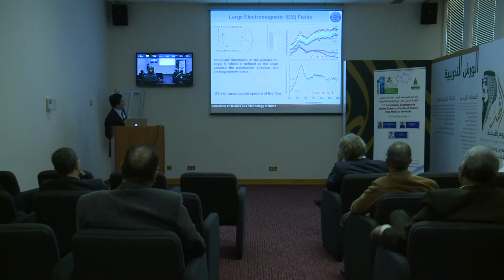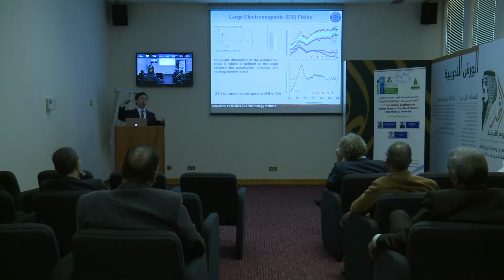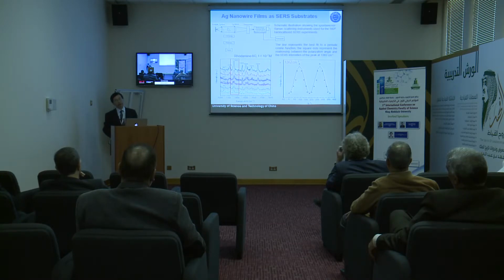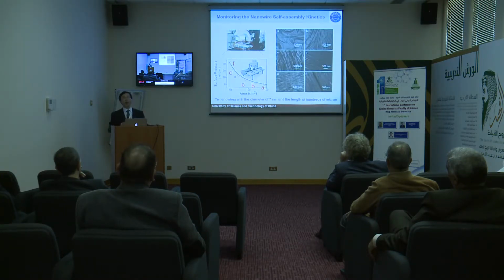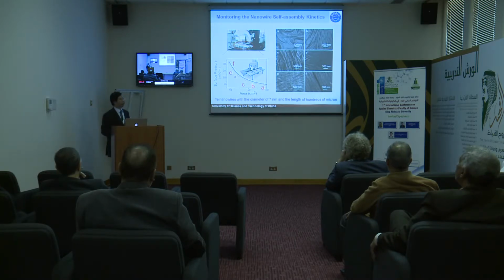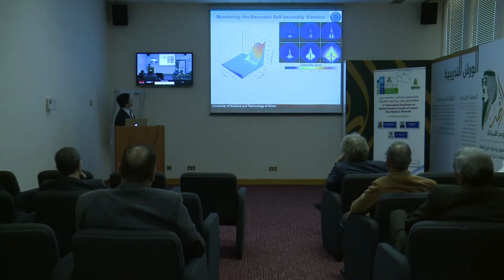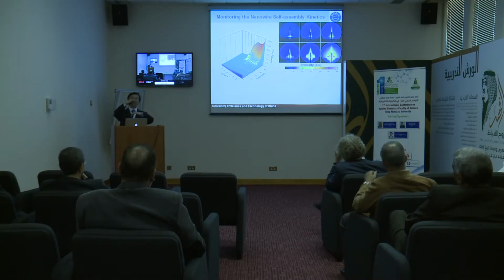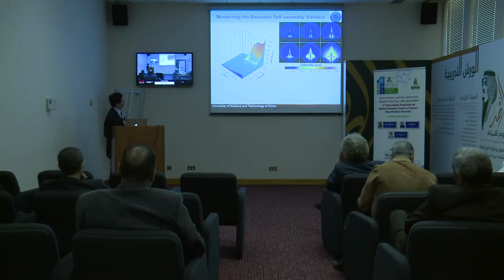If you get the ordered structure, you can shine light with different polarized angles on the surface of the silver nanowires, and you can tune the transmission efficiency. This example demonstrates that the assembled nanowire structure is much better for you to further control the property. Then we use small angle X-ray to identify the kinetics of the assembly of the ultra-thin nanowires on the surface. We use synchrotron radiation technique to monitor the self-assembly process of this ultra-thin nanowire on the surface of air and the solvent surface.